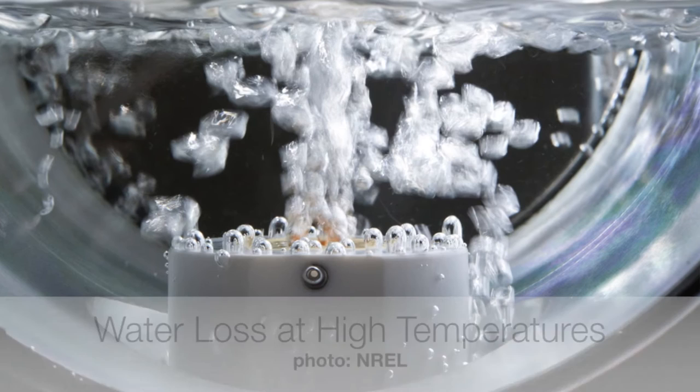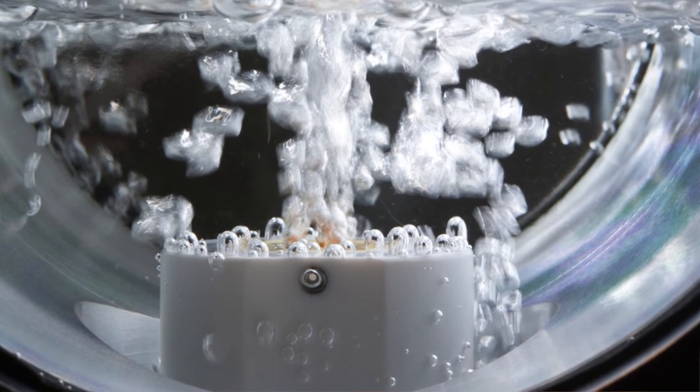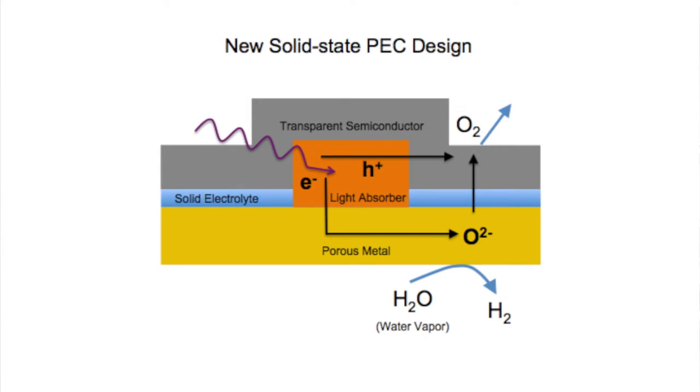Exactly. That's why you'd need a whole different device design to make this work. Here's how that could look. So the main idea here is the same as it was for a liquid PEC. But instead of having water conducting your ions, you have a solid electrolyte instead. These can only conduct at elevated temperatures, so they're perfect for this application.